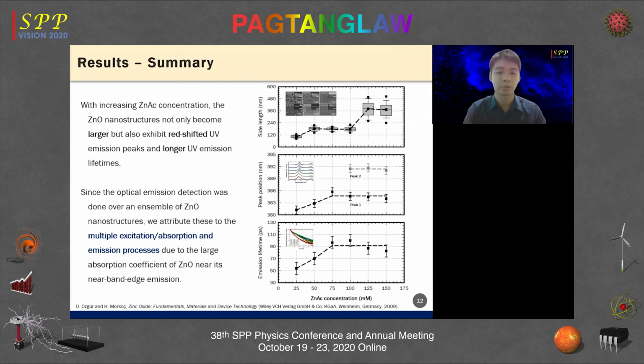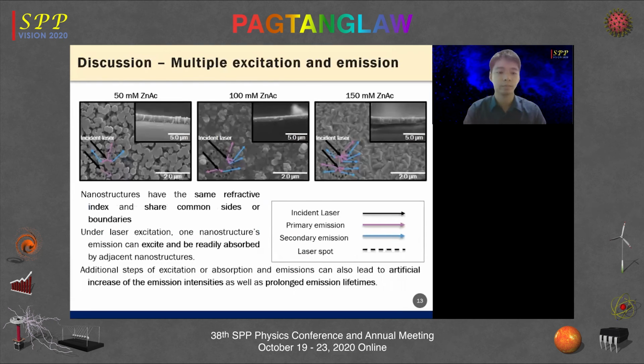Since the optical emission detection was done over an ensemble of zinc oxide nanostructures, we attribute these optical properties to the multiple excitation or absorption and emission processes due to the large absorption coefficient of zinc oxide near its near band edge emission. This phenomenon can be illustrated by the following diagrams.